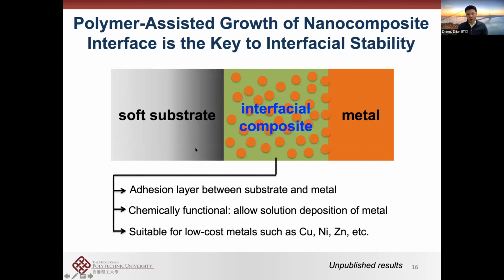So that's the kind of information that we come up with. To wrap up, PAM is a process which allows you to grow a metal from the bottom up through an interlayer of polymer, right? And in this interlayer, they form this kind of organic-inorganic composite structure, which allows you to adhere the metal, whatever grows on top, very firmly onto the substrates, right? And the key thing here is the growth is very versatile on whatever substrates, and you can use it for many, many different kinds of metals at low temperature. So that's very, very suitable for soft electronics in general.